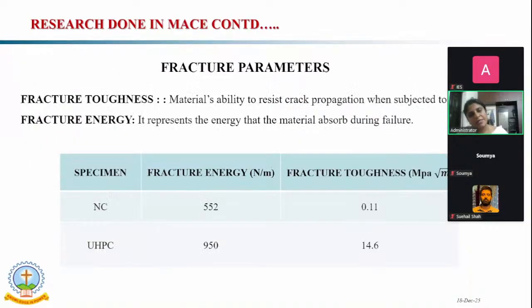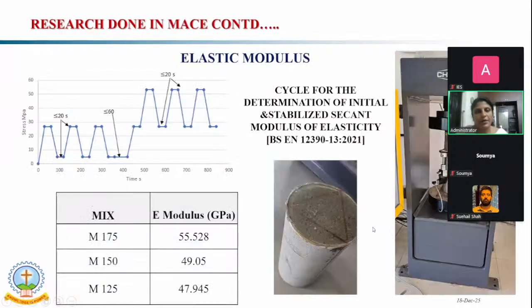We are considering the fracture parameters also. There will be a very high increase in fracture toughness by using the UHPC. To find out the elastic modulus of the developed UHPC mix, we have used the servo control machine itself, and we have considered 3 stages, with cyclic loading and unloading.